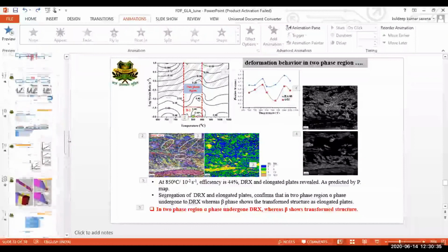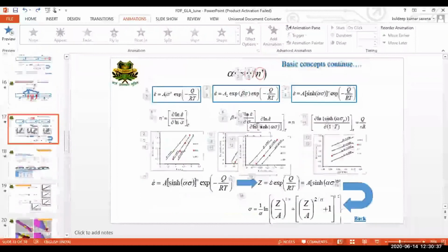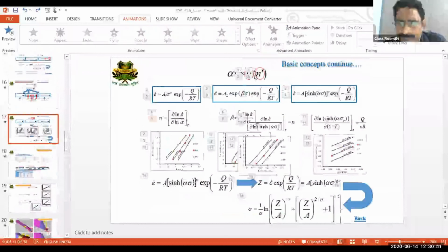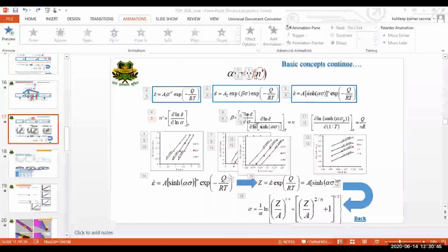Generally, you need to find the Q value, the activation energy. Correct. So for finding this activation energy, you need to take the sine hyperbola alpha sigma, and then 1 by T on the other side. You will take these two variables and then you find out. But how will you find this sine hyperbola alpha sigma?